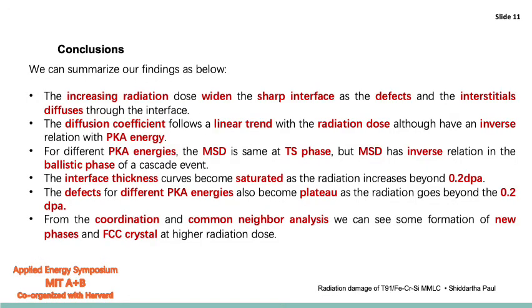So these are the conclusions that we have got from our investigation. Increasing radiation dose widens the sharp interface of the MMLC because of the formation of defects and interstitials, and those defects and interstitials diffuse through the interface from the T91 side to the iron chromium silicon side. We have also seen that diffusion coefficient, interfacial thickness, and mean square displacement have a linear proportional relationship with the radiation dose, but the diffusion coefficient and the interfacial thickness have an inverse relationship with the primary knock-on atom energy.